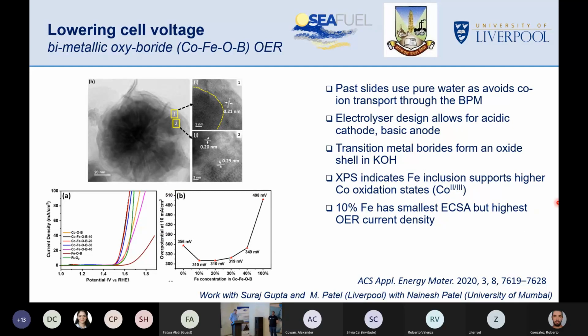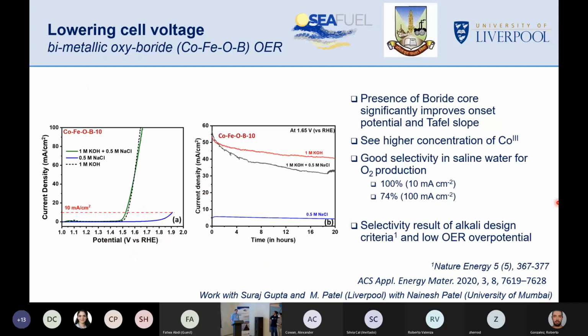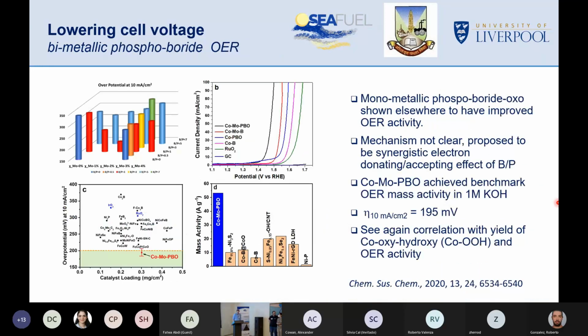The first point, yeah, I believe the nickel iron analogues have been studied. We've worked solely on the cobalt ones with Suraj, but yeah, the nickel iron ones are known. I wouldn't like to comment which is better. The OER literature is littered with problems. What you can't see because of the resolution is that this is a plot down the bottom here of catalyst loading versus overpotential. You can see, just look at the number of different catalyst loadings out there in the literature. So benchmarking catalyst 1 versus catalyst 2 is something that as a community we just need to get much better at doing and standardizing. So I wouldn't like to say what is better and what isn't. Apart from clearly we've fixed the criteria, so ours is the best, as everyone does.